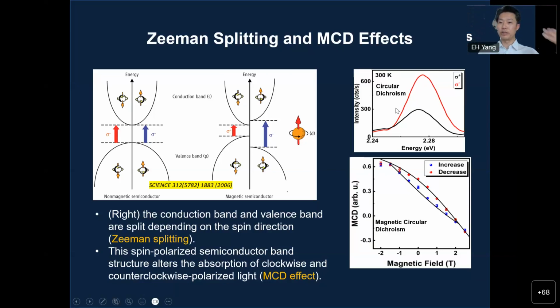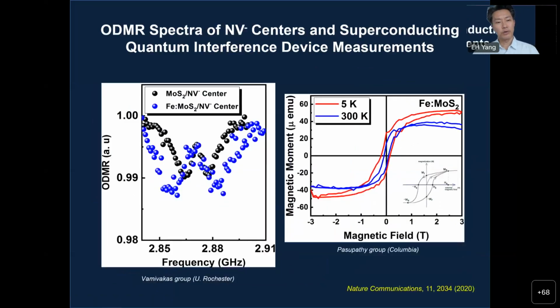That means your material is magnetic at room temperature, and this magnetic circular dichroism also shows this hysteresis loop by sweeping this magnetic field here. Okay, and then you can see this change of the circular dichroism here, right? Negative, then positive, and so on. We have performed several independent measurements to triple confirm this ferromagnetism that is exerted by the substitutionally doped atoms.